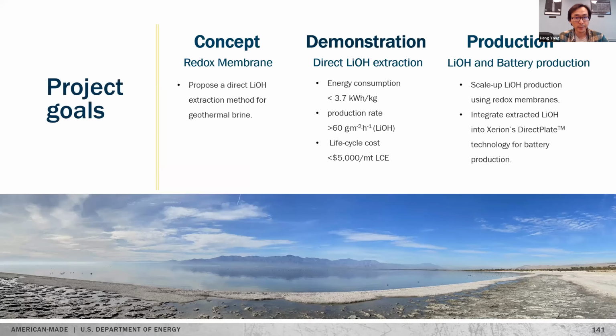Next slide, please. So our project goes at 3 different levels. At the concept level, we have proposed the redox membrane concept for direct extraction of lithium hydroxide from geothermal brine. In phase 2 and 3, we're working hard to demonstrate lithium hydroxide extraction with the goal of reaching energy consumption below 3.7 kilowatt hour per kilogram, with a production rate higher than 60 grams per meter square per hour, and with the life cycle cost below $5,000 per metric ton.